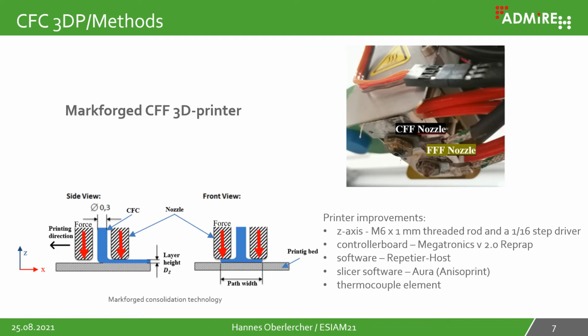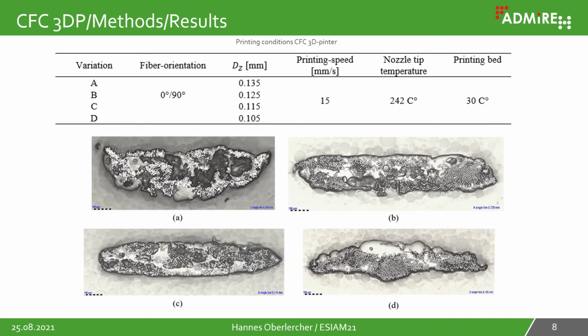The consolidation was controlled with the nozzle tip, and we reduced the layer height, and with the reduction of the layer height we give a higher pressure on the printed filament. Let's come to the printing conditions with this printer. We made a first experiment with 4 different variations. In every variation we reduced the layer height, for variation A from 0.135 millimeters to D 0.105 millimeters. The printing speed is about 15 millimeters per second, nozzle tip temperature 242 degrees, and printer bed about 30 degrees Celsius.